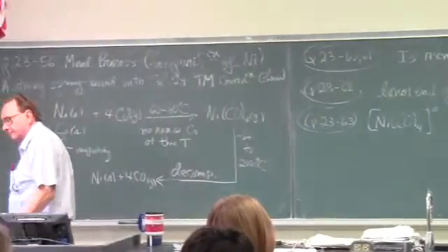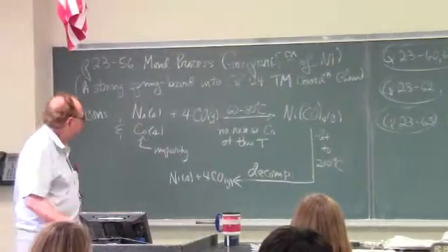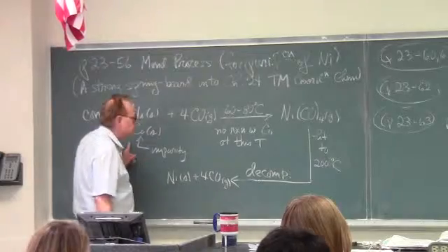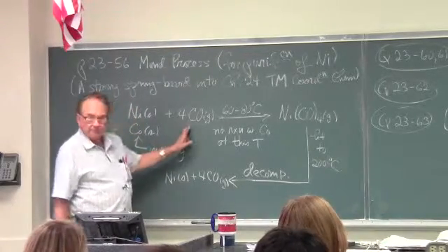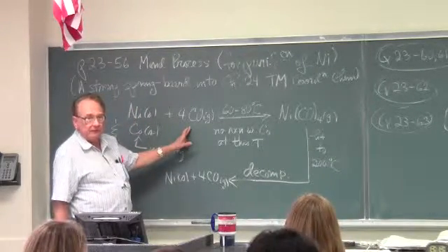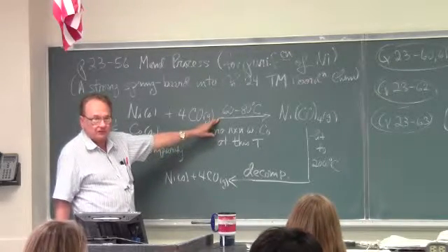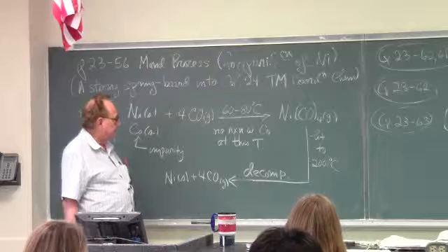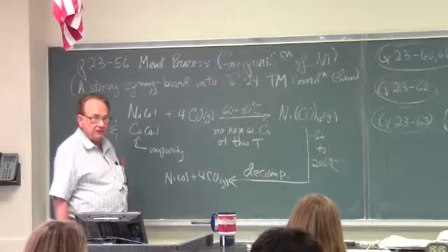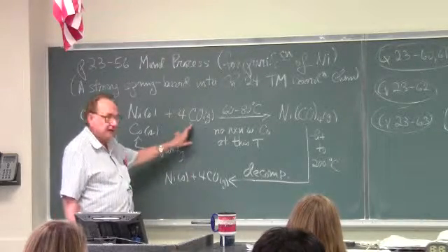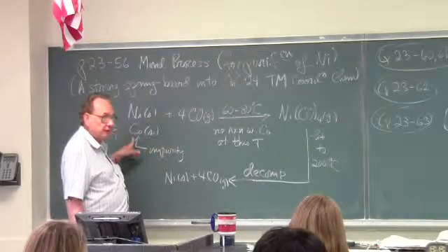The nickel sample, in this case contaminated with cobalt, is treated with a vapor of carbon monoxide at a fairly low temperature, lower than the boiling point temperature of water, 60 to 80 degrees centigrade. And at this low temperature, carbon monoxide molecules do not react with cobalt.